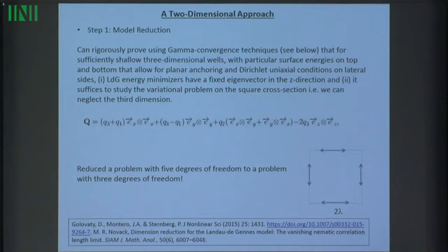so on the lateral surfaces you fix the Q tensor, and on the top and the bottom we use a surface energy. But for the right choices of these Dirichlet conditions and the surface energies on the top and the bottom, and in the thin film limit, it's actually enough to not look at the 3D box, but just to study the problem on the bottom cross section. So you've gone from a 3D domain to a 2D domain.